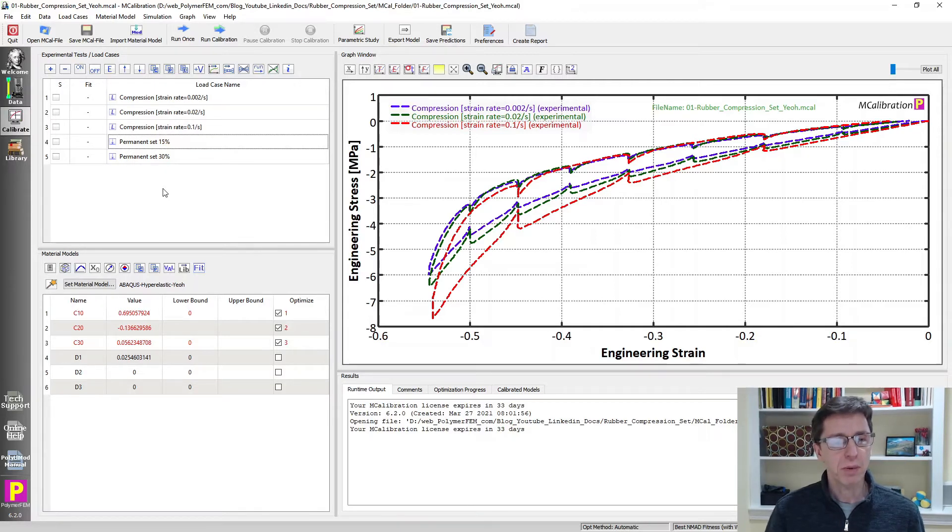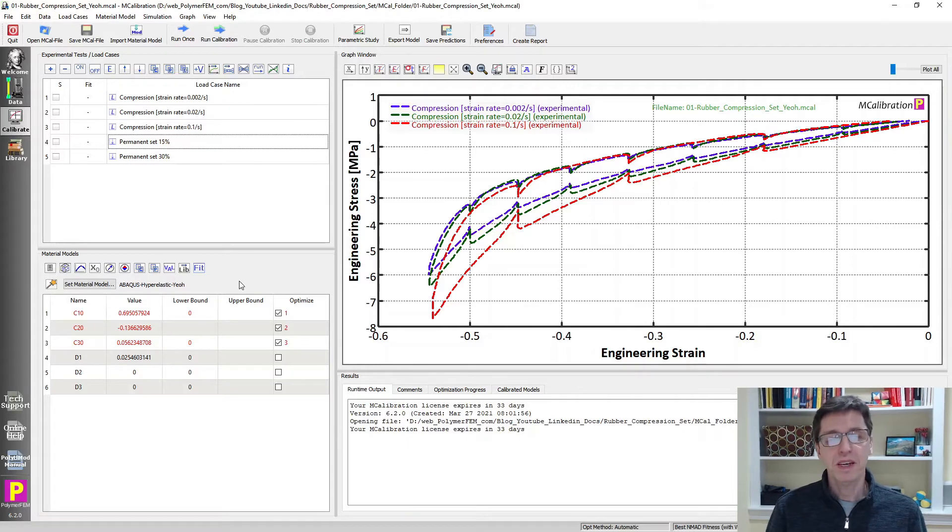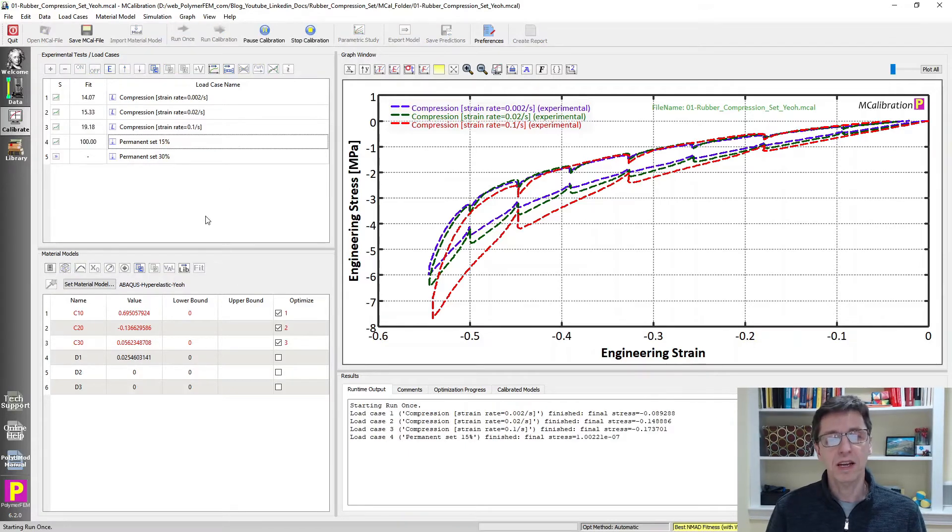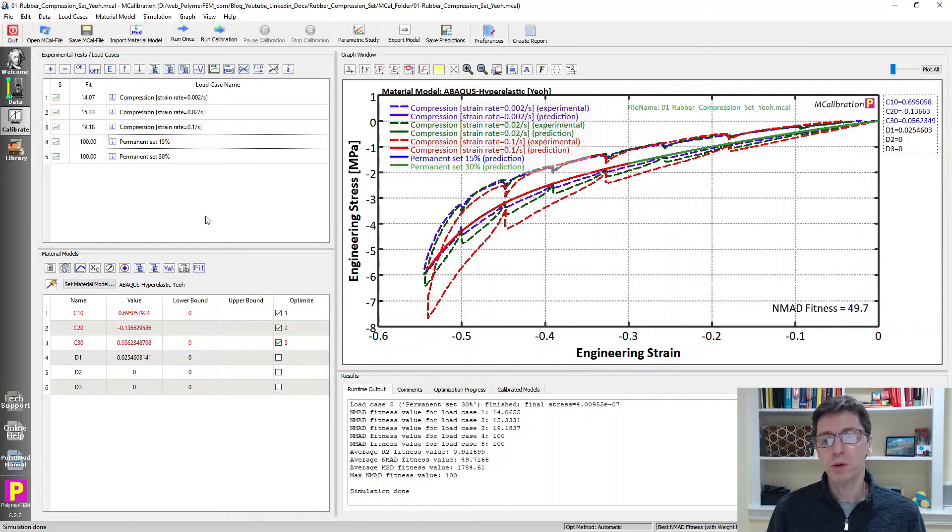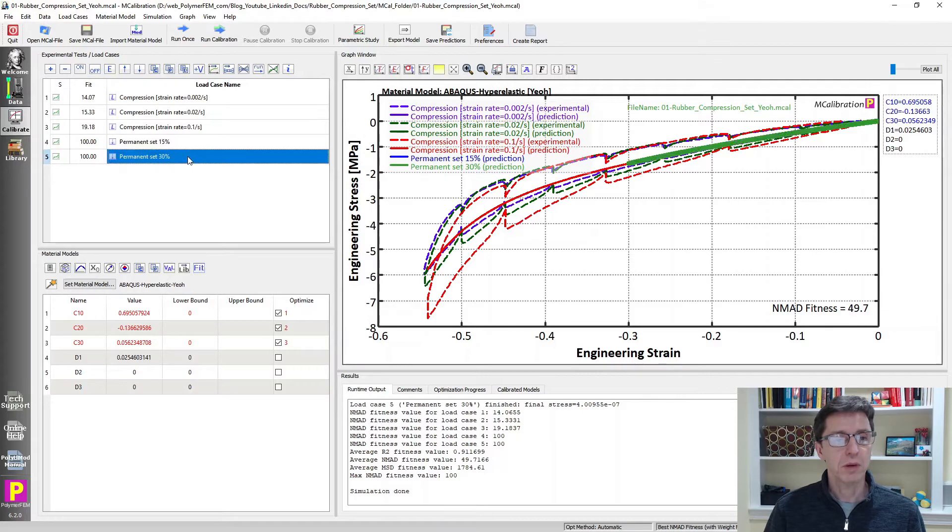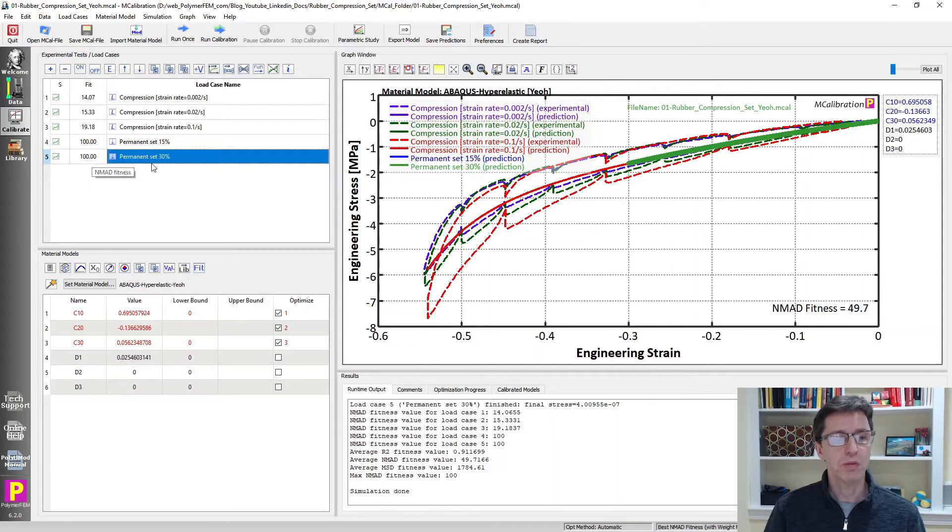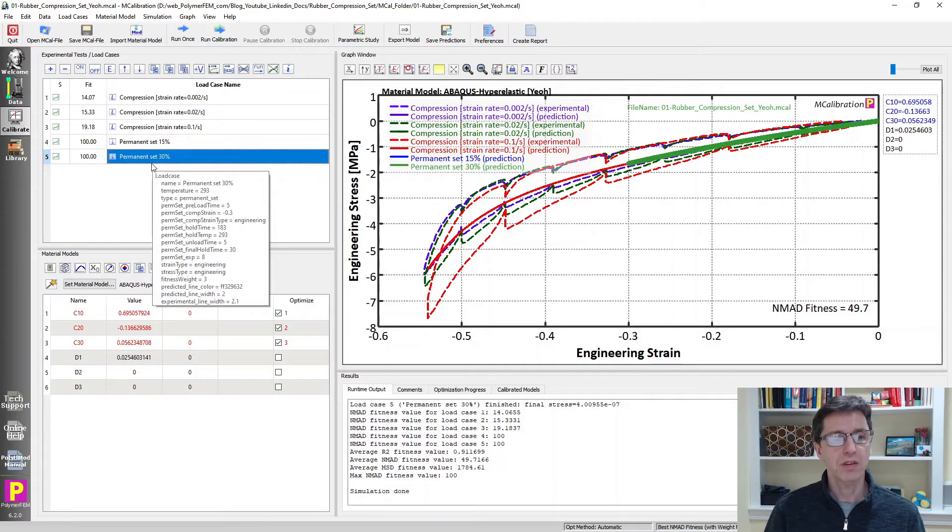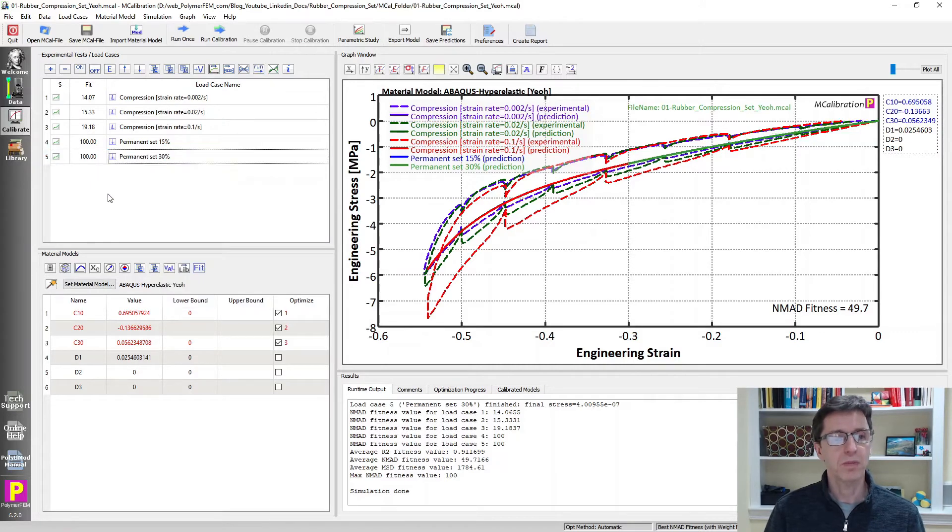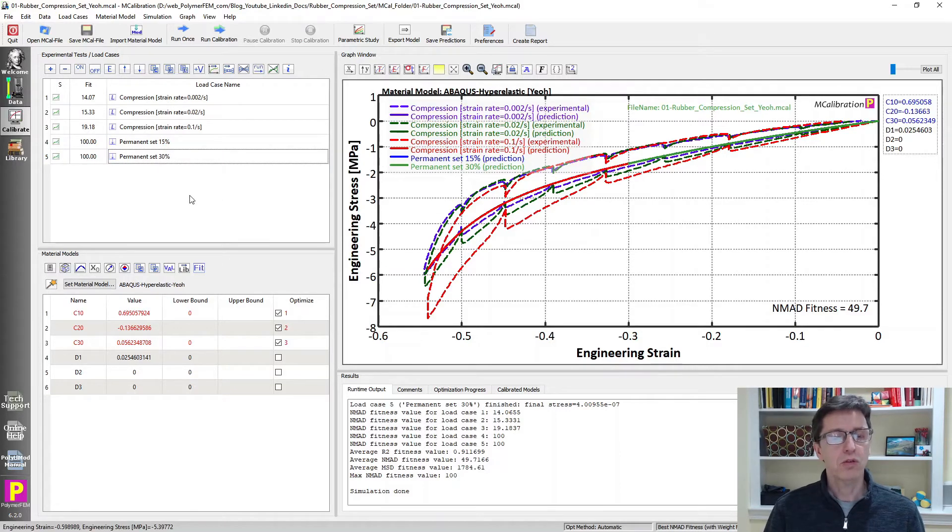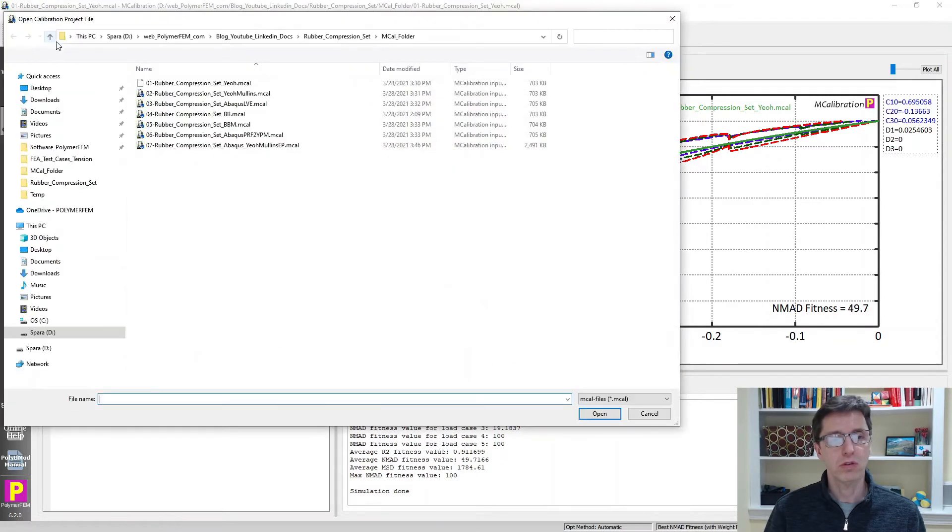So once you've done that though, you are good. You can simulate this, you can calibrate this. What I will do here is I will show you the predictions from a few different commonly used material models to see if they can predict the response to be measured for this particular rubber. My first example is a Yeoh hyperelastic material model. And you may say directly, at least I hope you would, that Yeoh hyperelasticity clearly cannot predict permanent set. It's an elastic material model. It may be non-linear elastic, but it's clearly elastic. And that's what MCalibration agrees with. You can see that the error here is 100 percent. That is, the predicted permanent set is zero, even though the experimental is a finite value. So that's how that's indicated. You also miss all the viscoelastic strain rate effects, etc.